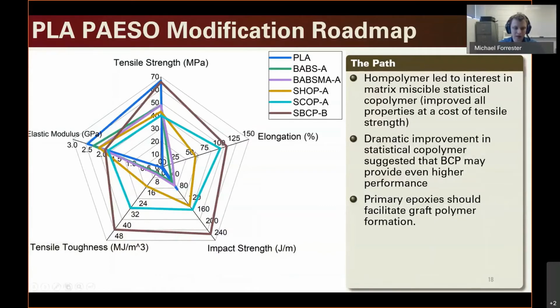Well, one of the immediate things that we think of is that our biosolvent is really good for the asphalt space, and it's very useful for the processing and production of the polymer, but it might be hurting us here in the production of these higher grade resins. And so what we did is we isolated the neat polymer, and that's what this brownish orange curve here is, and that's just the neat homopolymer. And what we saw is that we went from about an 80 to 120 joule per meter. So we increased the impact strength by about 50%. We further increased the elongation at break. So this material not only got much more tensily tough, but also got much more impact resistant.